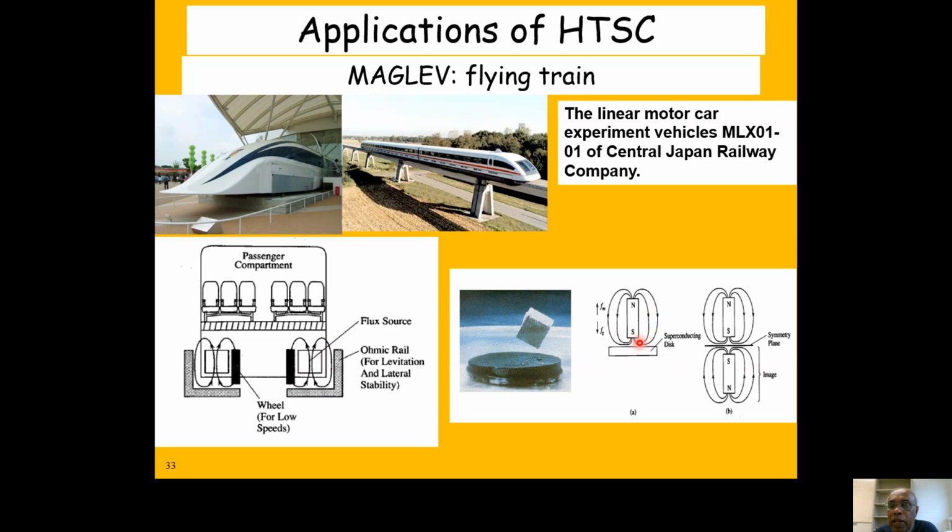That means these field lines are going to be flattened here, right? Because they cannot go through the superconductor. So you can see the flattening of the field lines. Where this flattening happens, you have a force on the magnet. That's the reason we have this levitation. You can also think about this as having image magnets, so the two magnets repel each other, right?